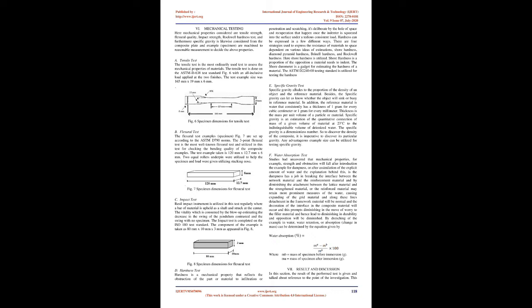During pouring, care should be taken to avoid the formation of air bubbles, and also while applying the pressure some mixture comes out from the mold, so care is to be taken while pouring. Then another OHP sheet was set over it. Then this entire arrangement was put inside a pressure forming machine called the compression molding machine, shown in Fig. 3, and allowed to cure for 2 hours.